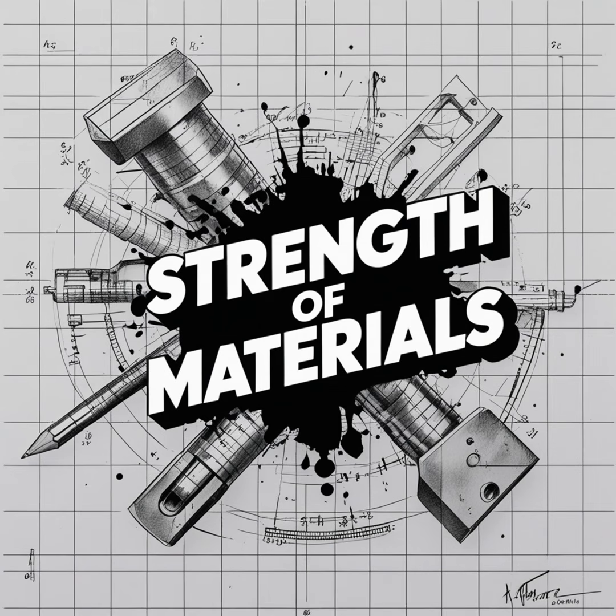Absolutely not. Really? Yeah, imagine a tiny crack forming deep inside a very thick plate of steel. When the metal right at the tip of that crack tries to stretch and yield to relieve the stress, it can't, because there's too much metal around it. Exactly. It is completely surrounded, boxed in by massive amounts of other solid metal. It can't easily shrink or pull inward in the thickness direction. We call this a triaxial constraint. Triaxial constraint. Got it. And because it is physically constrained from yielding, it behaves like our chalk. It snaps. Oh, but a thin plate has an escape route. Exactly. For thin plates, you are in a state of plane stress. The size of the deformation zone at the tip of the crack is roughly equal to the thickness of the plate itself. Okay. Because the outer surface of the plate is right there, just millimeters away, the material has freedom.